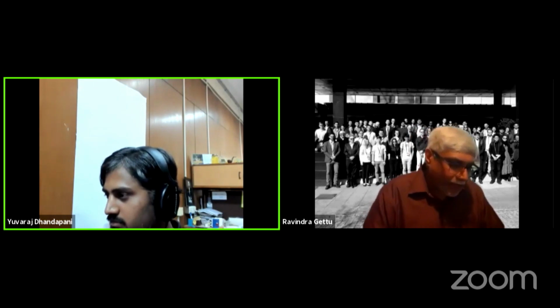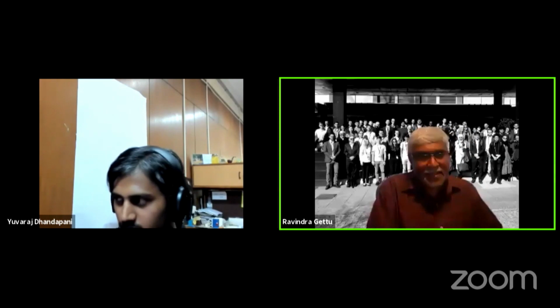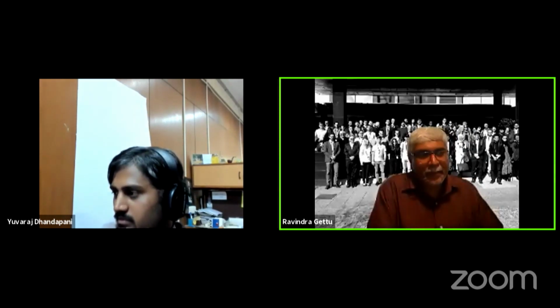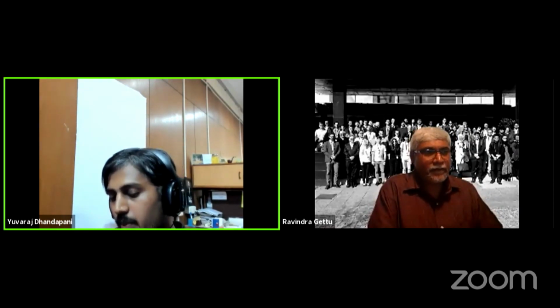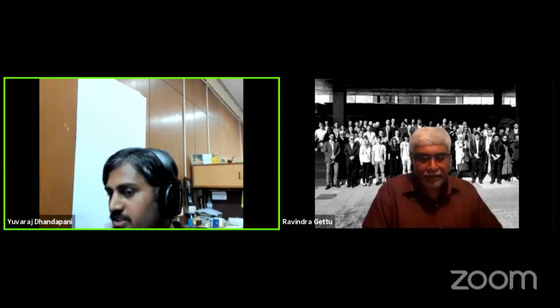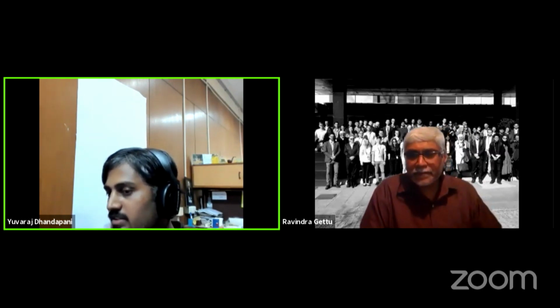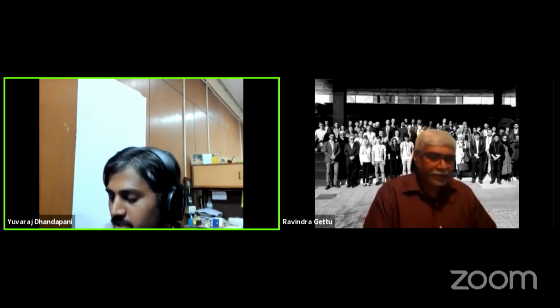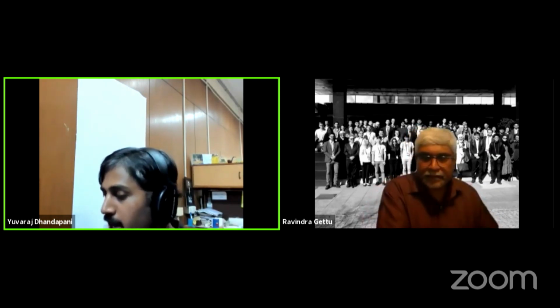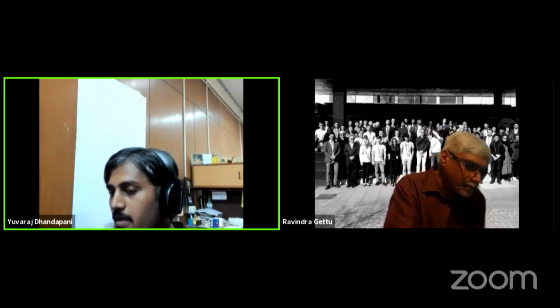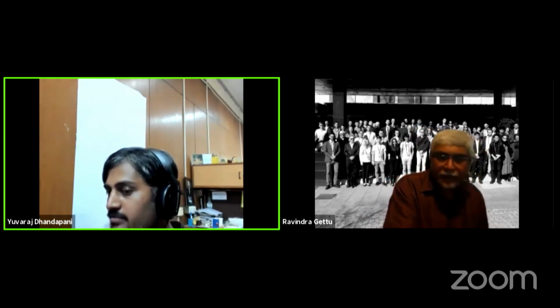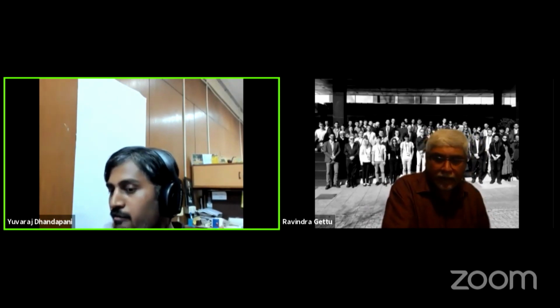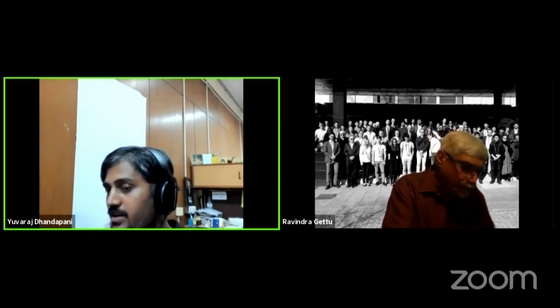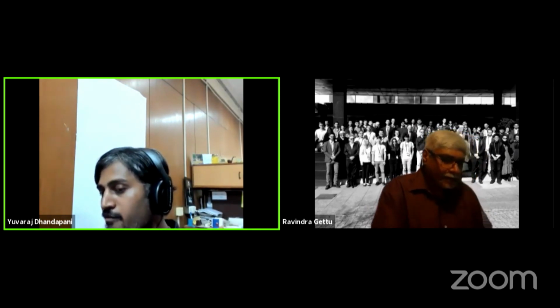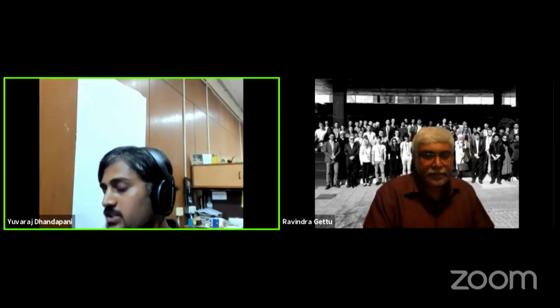Okay. And how about the fines? Does the grain size distribution of the SCMs affect their performance? Yeah, so we did an assessment of a range of different fly ashes. What we generally see is in calcium-rich mineral admixtures, when you make it finer, it does have an impact. But in general, for class F fly ash, we don't see a major impact just by grinding the fly ash to a finer extent on the main hydration curve. But eventually, using finer SCMs will improve the properties at a much earlier age in terms of durability.